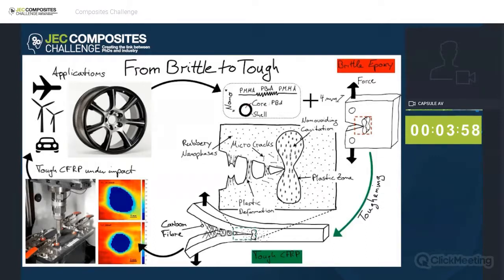So the inherent problem of carbon fiber reinforced epoxies is their brittleness. What can we do about it? Usually what is done, we can work on the layup. We can restructure the layup to generate more energy dispersive mechanisms. But why not tackle the inherent property, the matrix itself? One idea is that the high cross-link density is the origin of this brittleness. One idea would be to reduce the cross-link density for sure, but that will also affect a lot of other properties, and you will end up with a rubber.